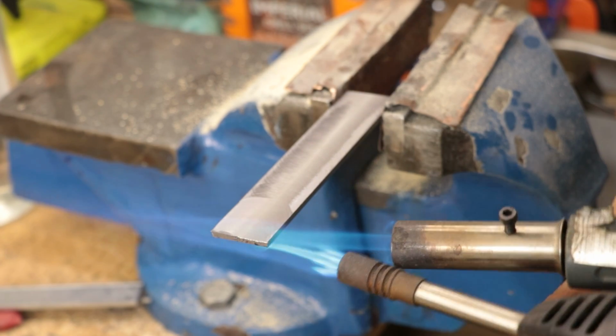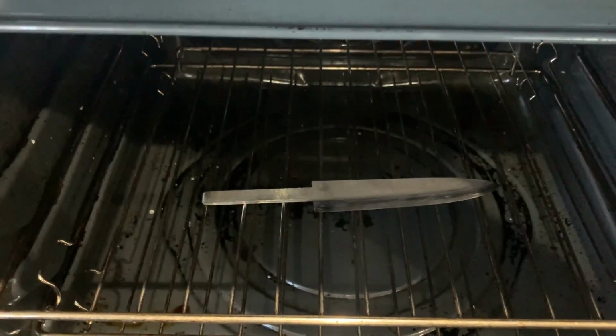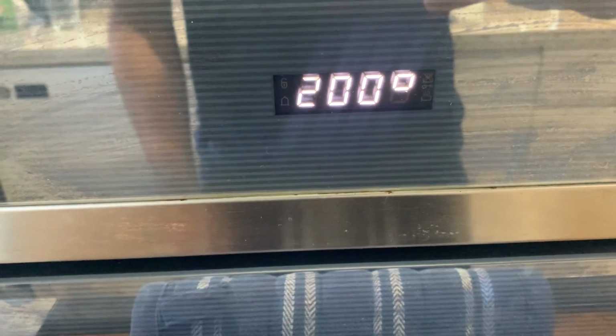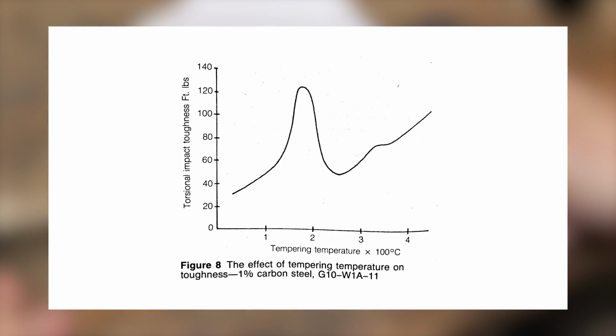The oxide colour changes depending on the steel's temperature, but I prefer to simply pop it in the oven and leave it for an hour. The amount of toughness that you get from steel, however, is going to be all over the place, and it's going to change based on the alloy. As you can see in the graph, it drops and rises several times, and you'll want to make sure that the temperature which you temper at is pretty much spot on. For example, with W1 steel, the difference between 180 degrees and 200 degrees for the temperature can represent a huge change and drop in toughness, so make sure that your oven is accurate.